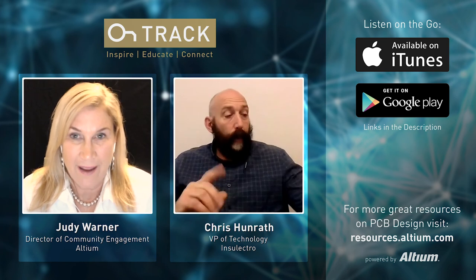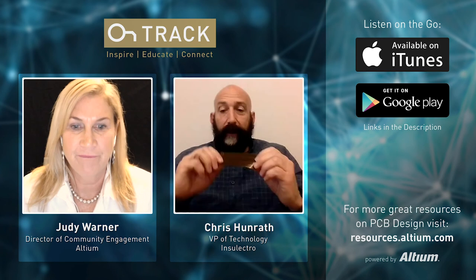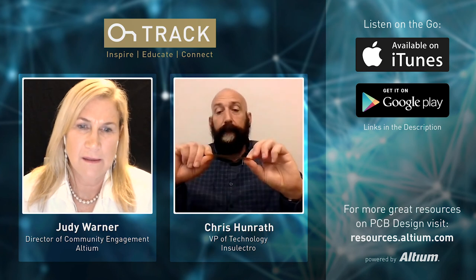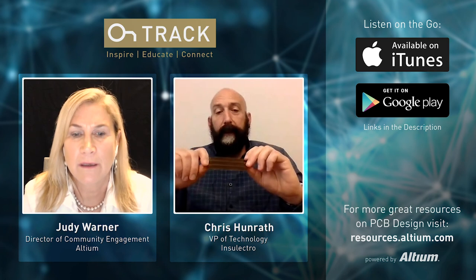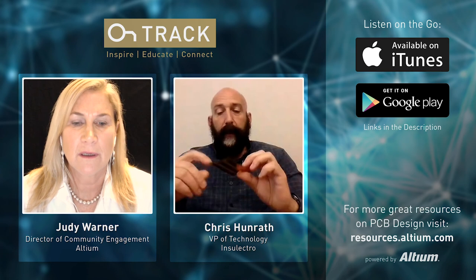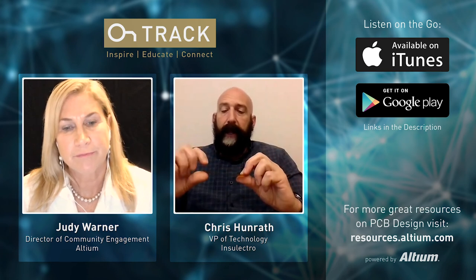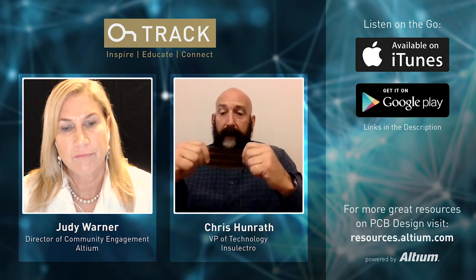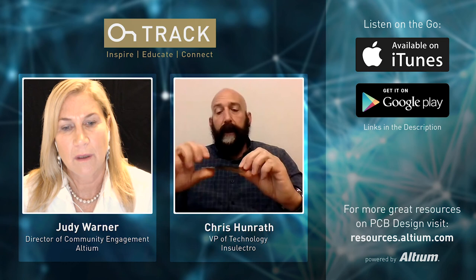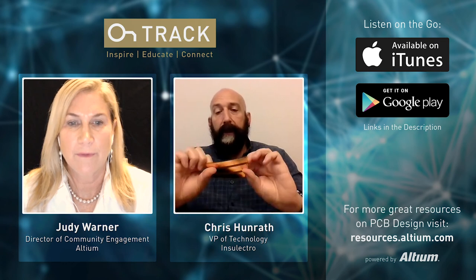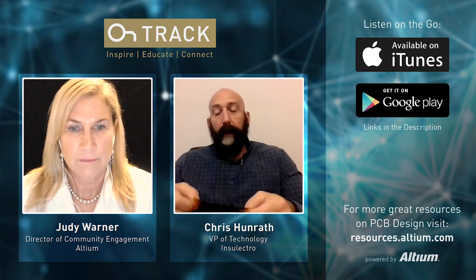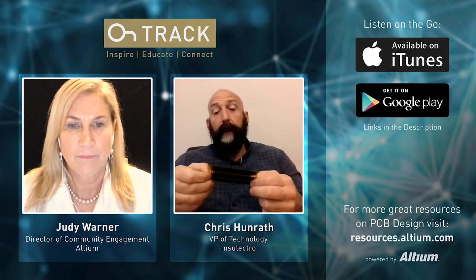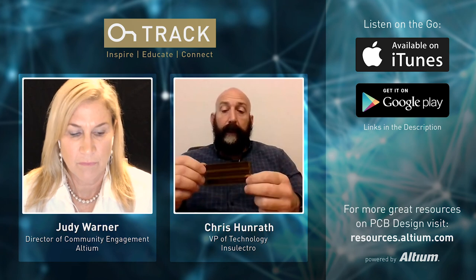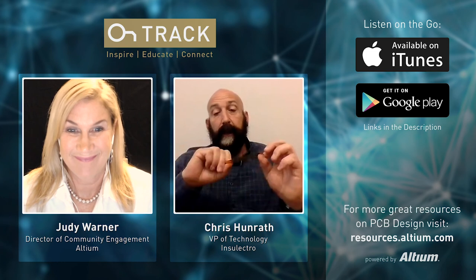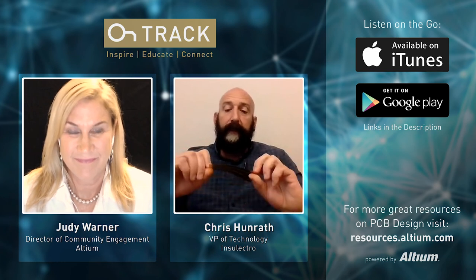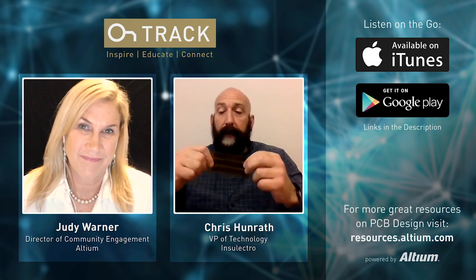Oh, one more material I did want to mention. This material actually is a Teflon Kapton laminate. It's called TK, Teflon Kapton. It's a Pyralux product from DuPont, and it has a core of Kapton to act as the XY stabilizer, but then it has a Teflon material on both sides. And again, this is a building block, but it's very low loss. Dk of about 2.5, with a very, very low loss. But unlike glass reinforced Teflon systems, this has no fiberglass, so no skew and no detrimental effect from the fiberglass. It's using a Kapton instead as the stabilizer.